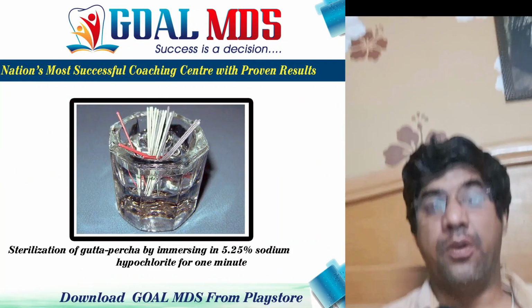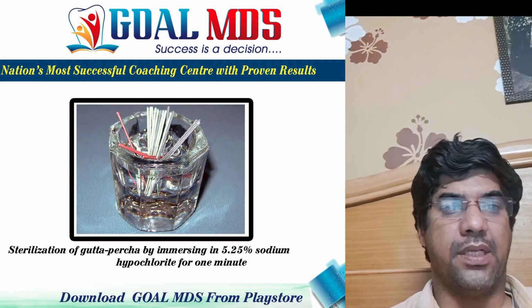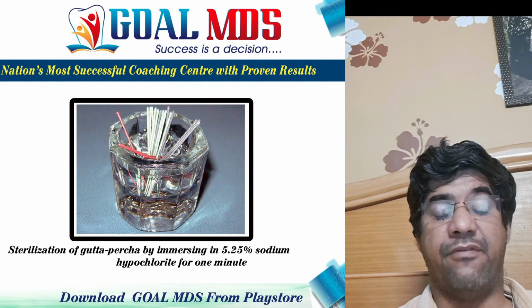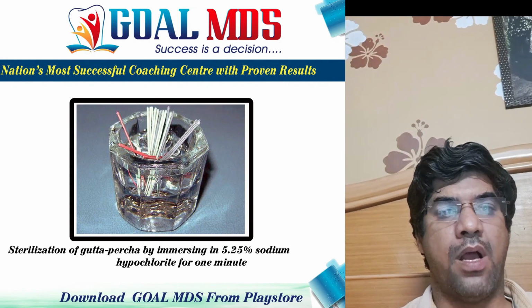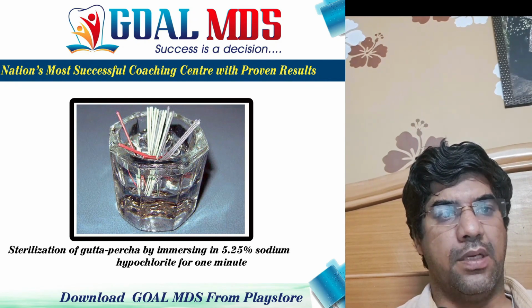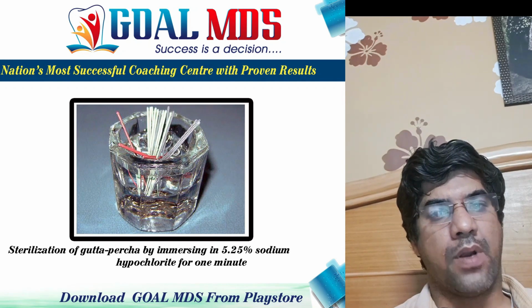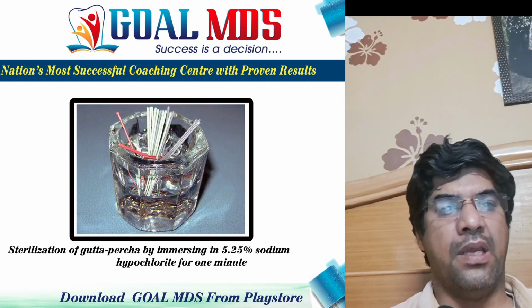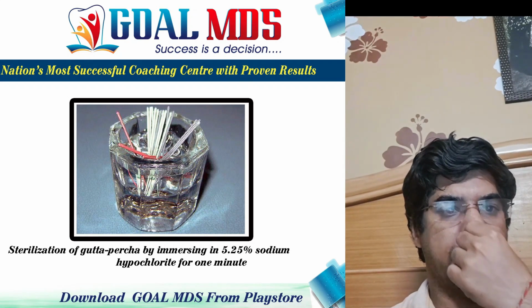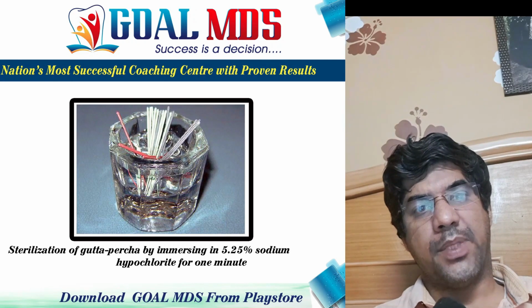An important point that you have to remember from your exam point of view is how will you disinfect the Gutta Percha points. The Gutta Percha points are immersed in 5.25% sodium hypochlorite for 1 minute. Remember the concentration: it is disinfected in sodium hypochlorite solution at 5.25 percent.